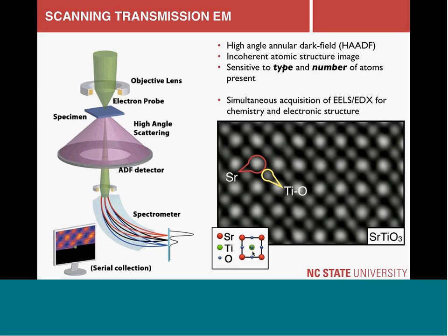All right. Simply by looking at how bright the blobs are, we see what sort of atoms are in those columns. So I can directly say that those are strontium columns and titanium-oxygen columns, from image intensity. There's another component in that, though, in that the number of atoms also matters, because we're seeing a projection of a three-dimensional structure, something maybe like 20, 30, or 100 some odd atoms in projection at those positions. So it's not flat atoms.